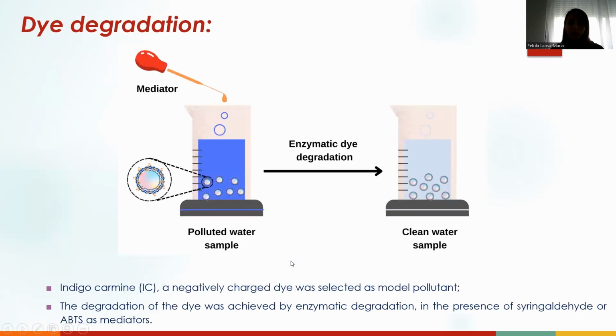In order to test the potential application of the immobilized laccase in water cleaning, the composite biocatalysts were put in contact with an aqueous solution of indigo carmine at room temperature and under shaking. Small volumes of ABTS or syringaldehyde were introduced in the system in order to facilitate the enzymatic degradation of the dye. The discoloration degradation efficiency was assessed by measuring the decrease in absorbance at 610 nanometers, which corresponds to the dye absorption maxima.